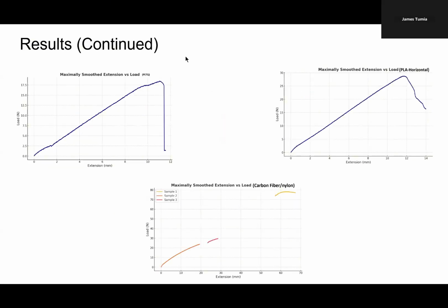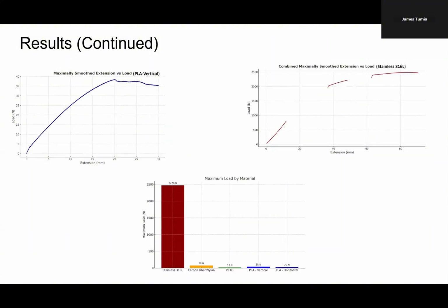As shown below, here are some graphs that were able to be created that show extension versus load. We came into some trouble when we tested the carbon and the steel pyramids. This was due to memory storage issues. Since we were taking so many data points, we had to stop and restart the same trial, which caused an error in the system, which is shown by the jumps in the graphs.